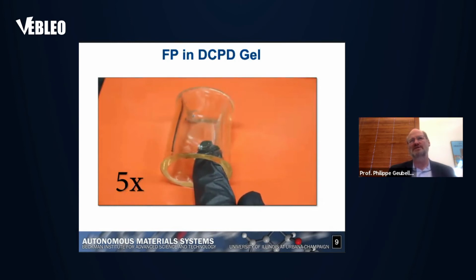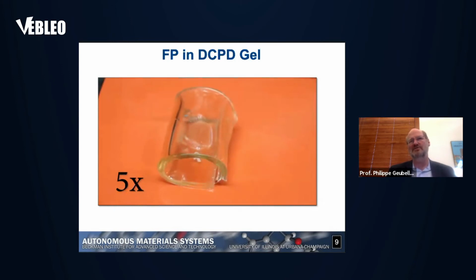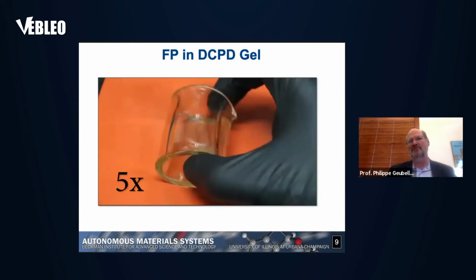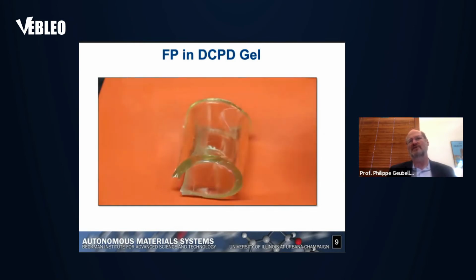And so what you can see is that by introducing a thermal trigger with just a soldering iron, you can see that the front propagates to the part after you give it whatever shape you want, and then you end up with a fully polymerized part.